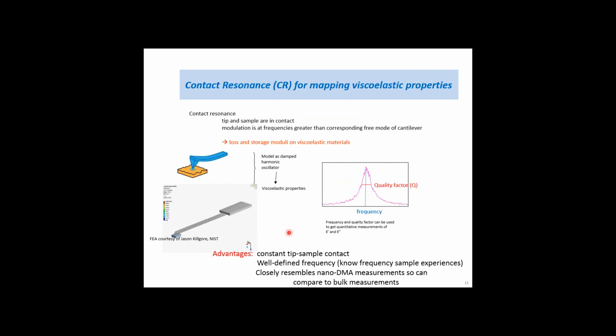Okay, so let's talk about this method of contact resonance for mapping viscoelastic properties. Contact resonance is a method where the tip and the sample are in contact, as shown here. And so the tip-sample contact is then oscillated at frequencies greater than the frequency of just the free air oscillation of the lever. So here I have a very nice simulation, courtesy of Jason Kilgore from NIST.